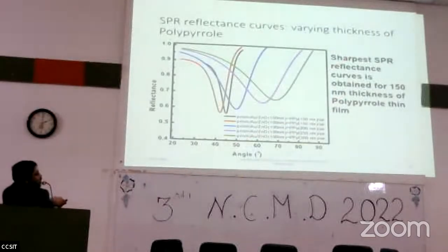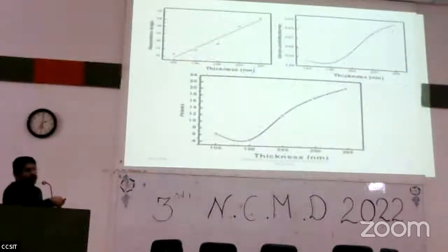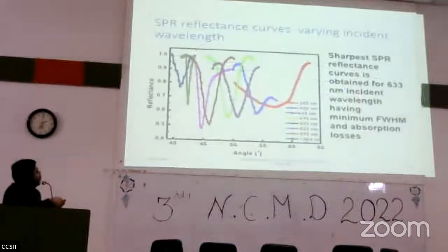Now we vary the thickness of polypyrrole from 100 to 300. Again, we see an increase in resonance angle. There is a change in minimum reflectance value from 100 to 150. So we can plot it separately for the three variables, that is minimum reflectance, resonance angle, and full width at half maximum. Again, it was observed that 150 nanometer is our optimized thickness. Then we also varied the incident light wavelength. It is observed that around 633 nanometer there is the sharpest curve.